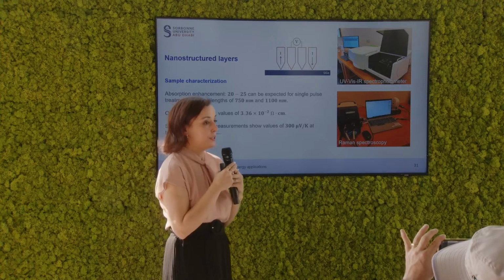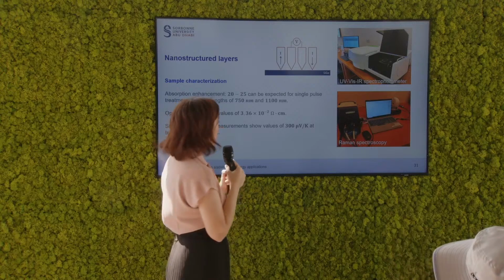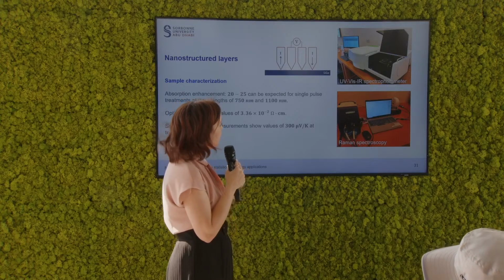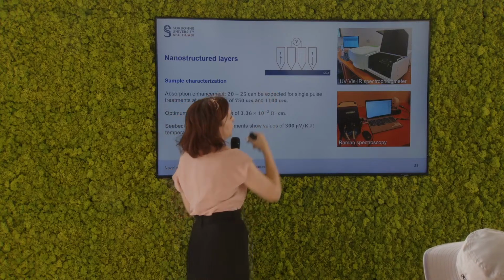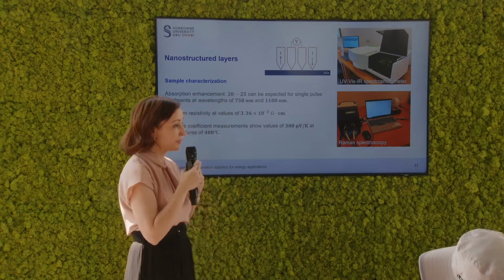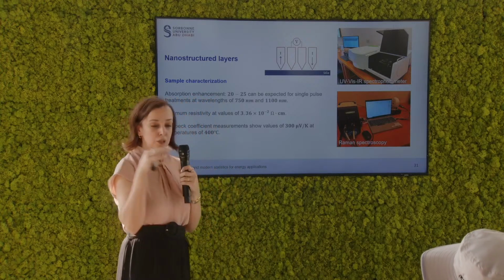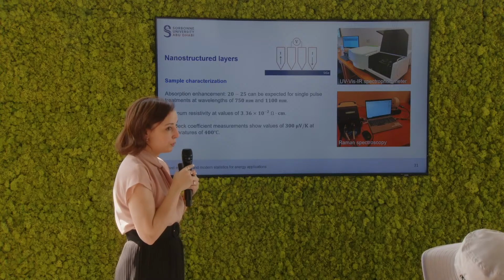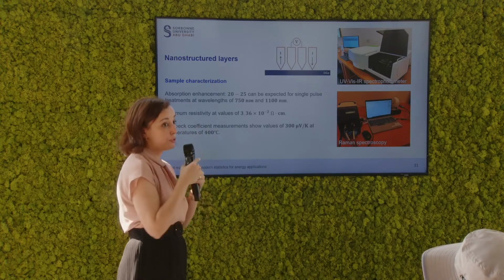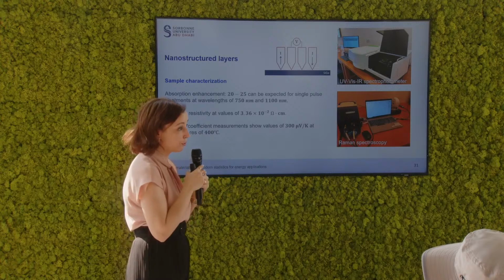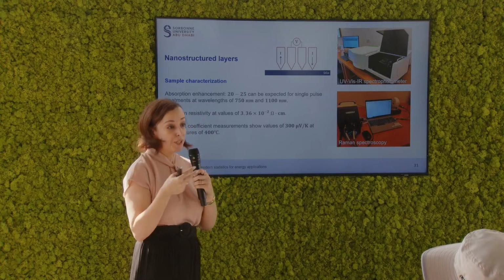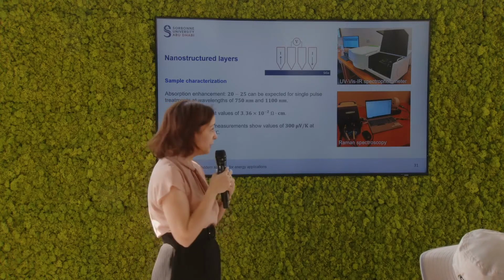We also conducted some resistivity measurements for our samples. And resistivity measurements are conducted using a 4-point probe, which I have an image for here just as a schematic. You use 4 probes, you bring them in contact with your layer, you pass current through the outer 2 probes, and you measure voltage through the inner 2 probes. And from that, you can calculate the sheet resistivity of your material.